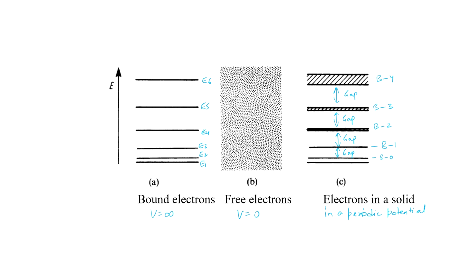In this lecture we have tried to explain how the bands form in materials, which form by interaction of the electron with the lattice and the electron undergoing diffraction in the lattice at the boundary of the first Brillouin zone, and at those points the energy state splits into two. Because of the standing wave solution of the electron wave, we create two wave functions, psi plus and psi minus. Correspondingly we will have E plus and E minus, two energy states, and the difference between those two energy states is the gap, and the formation of these bands and the gaps between them continues until the higher energy.